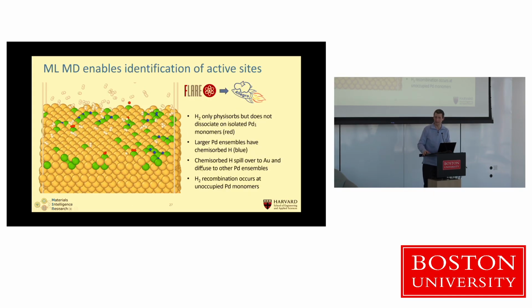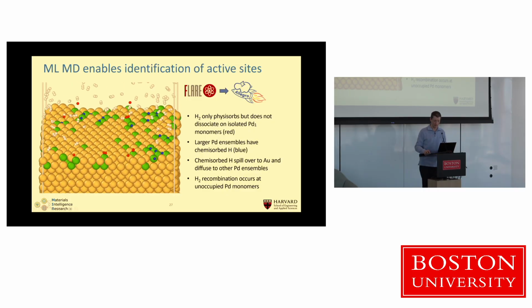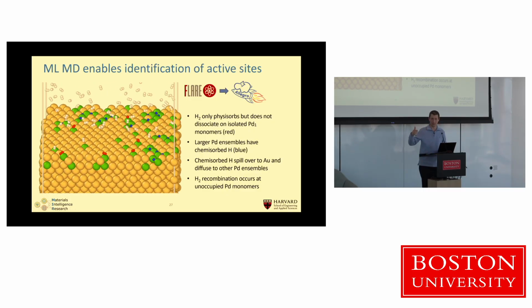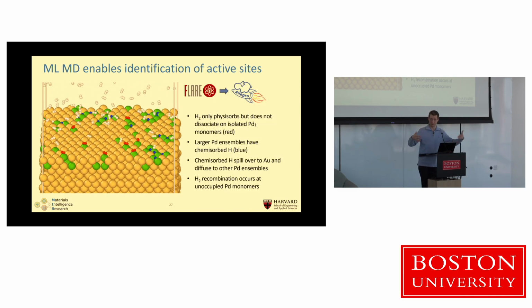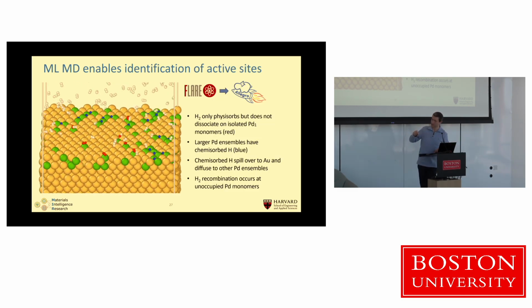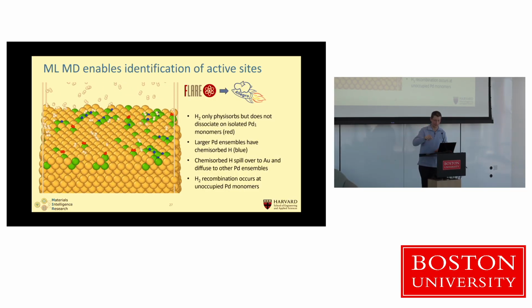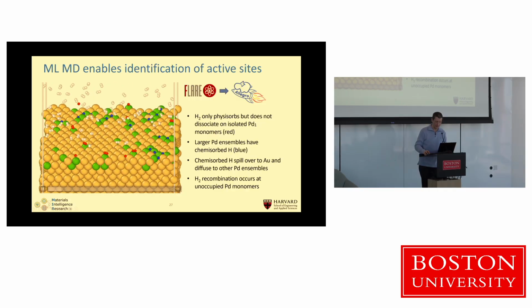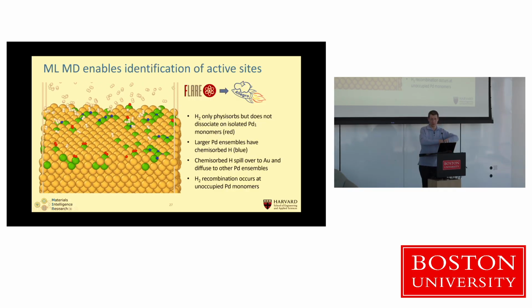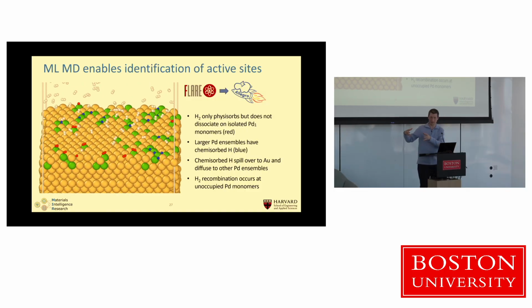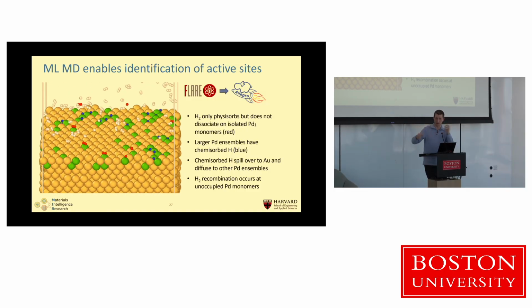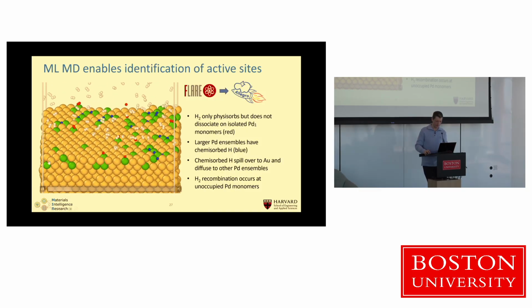And then you can do more complicated things like start playing with alloys and ask what are the active sites, what is actually the catalyst doing, like on which site does the molecule adsorb, change into a different molecule, does it move around the surface? And so we can decompose our simulation now that it has seen all the data and actually has all the events there. We can establish its correctness by comparing to experiment macroscopically, but then also ask it to look at individual atoms and molecules and figure out what the mechanisms are. And so we can find out that, for instance, individual palladium atoms are the sites responsible for recombining and desorbing molecules, and islands of palladium are the sites that are responsible for absorbing and dissociating molecules. So you can get this whole reshuffling of the chemicals.